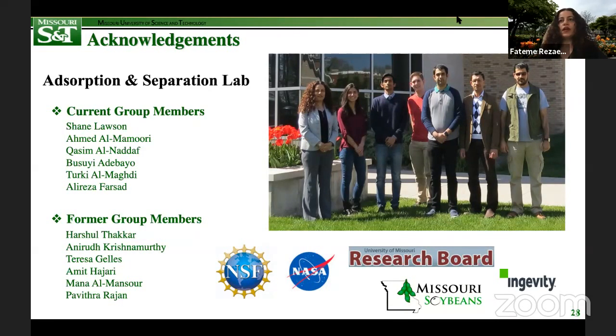So that's in fact a good question, and it goes back to my note about investigating the actual performance of these materials under realistic cyclic conditions. Yes, we investigated the performance of several of these monolithic structures over multiple adsorption-desorption cycles, mainly at low pressures and under different temperatures. We did not really observe any noticeable capacity loss for our adsorbents, especially for the most robust adsorbents. But for some other materials, especially aminosilica adsorbents in the form of 3D printed monolithic structures, we observe some capacity loss due to amine leaching.